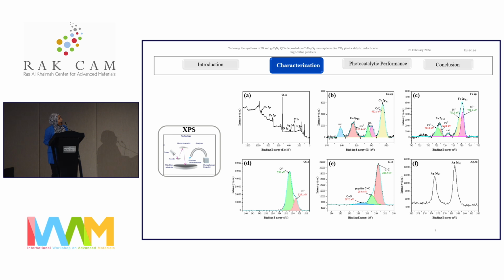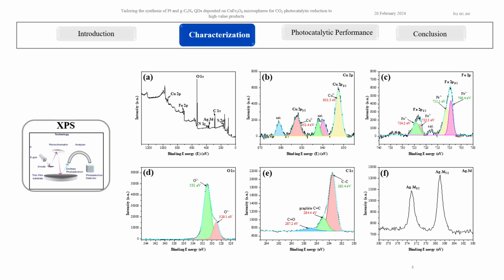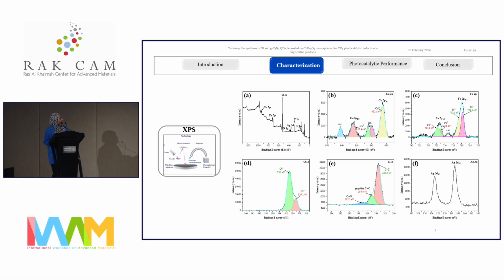Then we conducted XPS to determine the chemical environment and the oxidation state of the elements. For copper, we found that we have metallic copper. For iron, we have iron +2 and iron +3 environments. For oxygen, we have oxygen -2 and oxygen -1 environments. For the carbon, we have carbonyl, carbon-carbon double bond, and carbon-carbon single bond. While for silver, we have metallic silver and silver oxide.